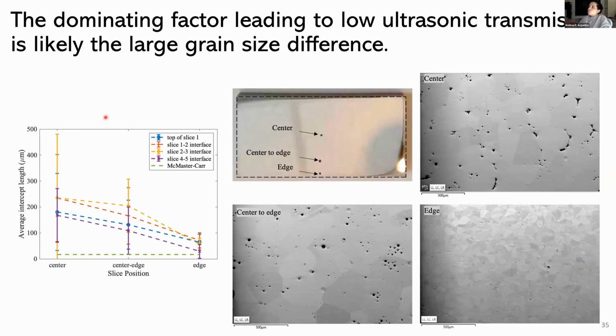But what we saw once we went to the analysis of that microscopy data was that at the very center, you had much, much larger grains, and you can see those boundaries in the image on your screen. Essentially, we were going from grains that were around 250 microns in diameter down to grains in the 75 micron diameter range. So that significant change is what was dominating the response that we were seeing with ultrasound.